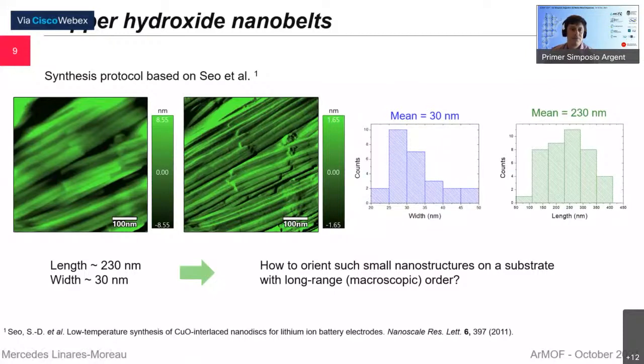Thank you, Matthias. These are really good questions, actually. For the monodispersity, I have some measurements that were taken from AFM topography. So the dispersion in width is quite low, but in length, we have from 100 to 400 nanometers. I mean, this definitely will have an influence on the highest degree of orientation that we can have.